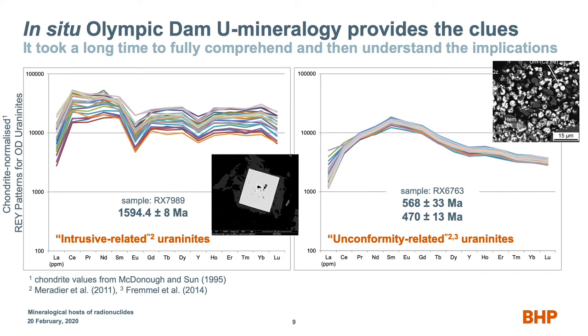But the more important thing is the rare earth patterns that these things contain. And these rare earth patterns are distinctive of the chemistry and the physical chemical conditions under which these uraniums precipitated. The nice euhedral early uraninites have a pattern that's very distinctive of uraninites that form from a high temperature hydrothermal solution. Beautiful. Then we look at these things that are a lot younger, and they have a completely different rare earth pattern. For those, having looked at uraninites around the world and classified them, we know that they have a signature that's more similar to an unconformity-related uranium deposit. What that really means is a lot lower temperature.